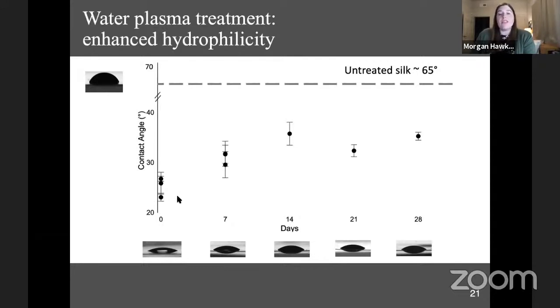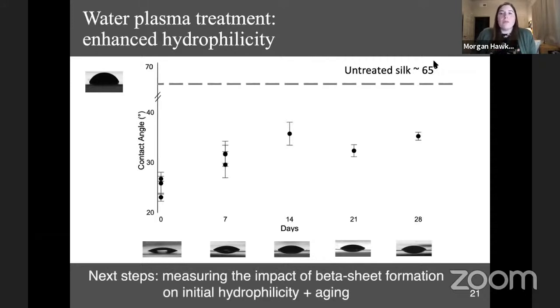And after this initial treatment, we aged the samples just under ambient conditions. So they're just sitting at room temperature, nothing too fancy. And what we see is that the film contact angles appear to increase. We have fewer data points at these longer times, which we're working on establishing by collecting additional technical replicates here. But we saw some evidence of hydrophobic recovery as a function of aging, and the surface appears to plateau around 35 degrees, though we definitely need to continue to collect more replicates. So we're trying to see if these results are more reproducible, and my student is seeing some really interesting results.